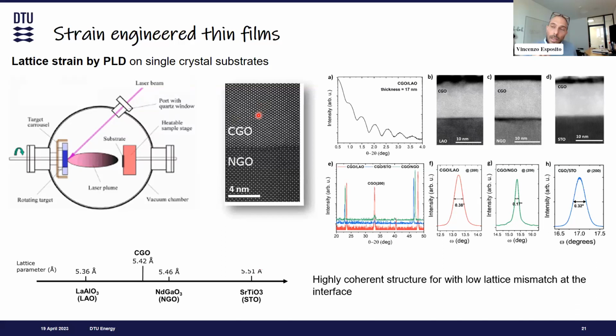And when we tune the deposition using different crystals with different orientations and different lattice parameters, we can actually get into a field where we can even control the lattice strain at the nanometric level. So we are basically taking our fluorite structure in a strain condition, which is imposed by the substrate. And this is what I will show you in a minute when we deposit the CGO on different substrates, for example lanthanum aluminate, neodymium gallate or strontium titanate. They have a different lattice parameter, and the crystal grows with a different tension, with different strain at the lattice level. This is not the only possibility.